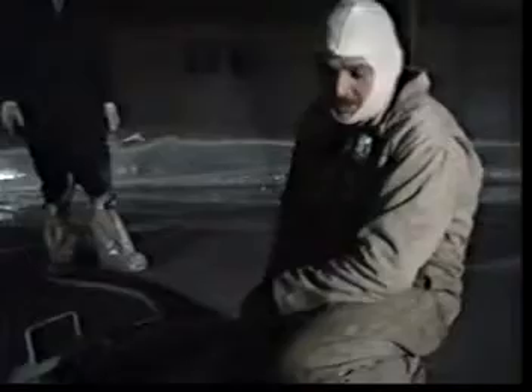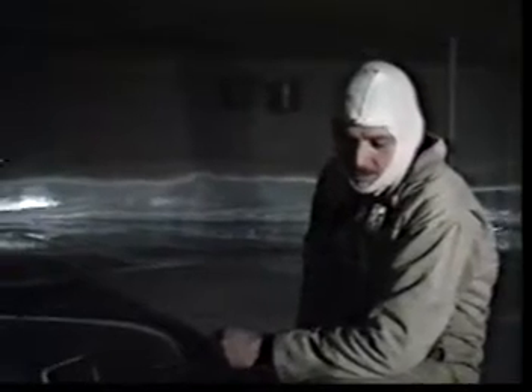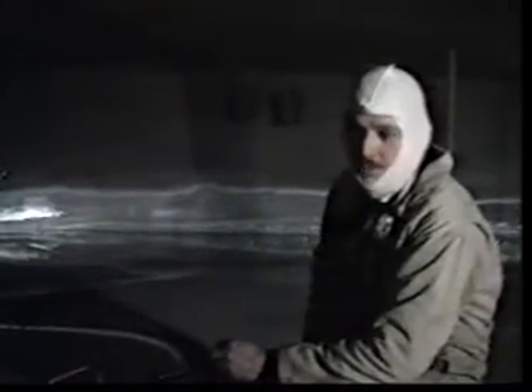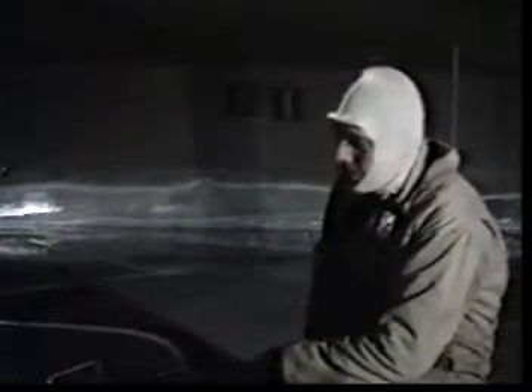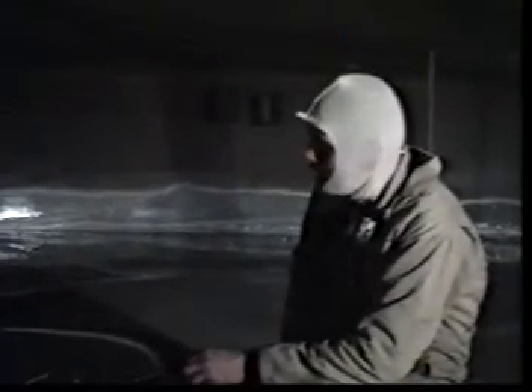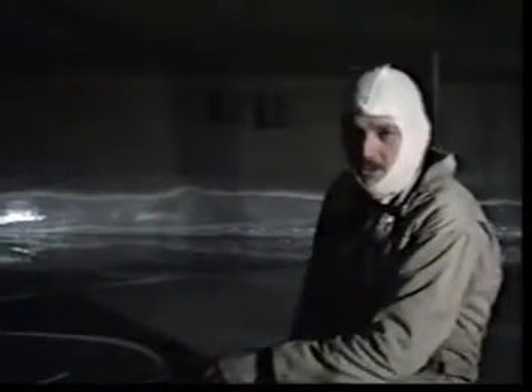So we're assured that we have our millage thickness per coat. The profile on the floor is running between 5 and 6 because of the severe pitting. If you take a look at that, you'll see that it's quite deep. And because of that, we're using a little bit more material than we actually should be. We're required for a 3 to 4 mil profile, and we currently have a 5 and 6 overall. And I'm going to let him go ahead and continue spraying because the material's in the line. It's going to start to stiffen up. So go ahead, Joe.